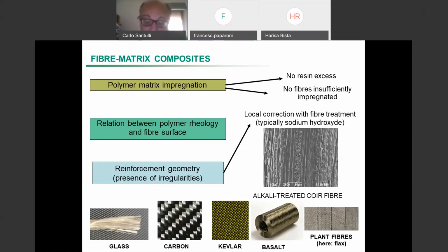Then you need to study the polymer rheology. We have talked already about the rheology, the way that the polymer flows and the way that the polymer is able to impregnate those fibers. So we have these kind of fibers. The fibers can be treated, for example, with alkali, with sodium hydroxide. This is again coir, which is treated with alkali, therefore sodium hydroxide in most cases, which produces some voids, some porosity, and reduces the irregularity, but you don't get a very regular fiber like it was the case for glass, carbon, Kevlar, basalt. You get something which is irregular because it comes from a plant, because it has some limitations of lengths.